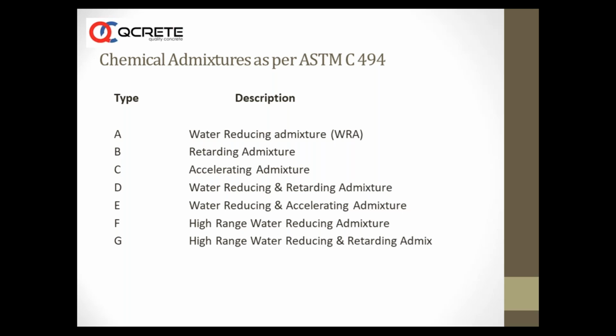The next version is type G, which is the most popular version for ready mix companies. All over the world, ready mix companies are very fond of this kind of admixture, where you can transport the concrete, place the concrete for up to 3 to 3.5 hours, because it has an element of retardation, very good slump retention, and good water reduction. So type G is HRWRA and retarding, and very popular. Most of the ready mix companies and concrete producers throughout India are using type G admixture.